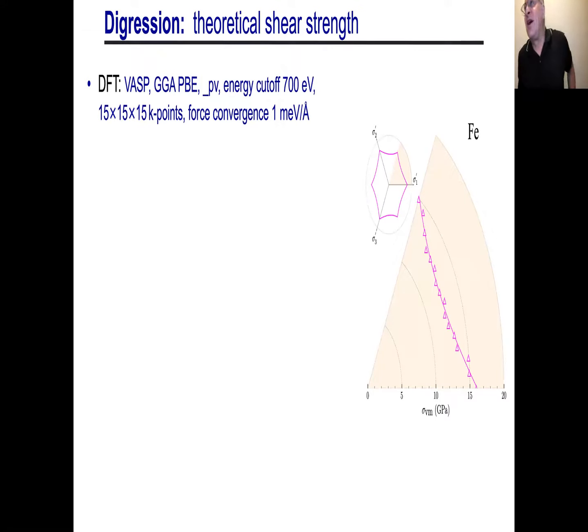Okay, I've got 2 quick digressions and then I'll get on and start showing you a lot more data. First, all the DFT calculations I show you are going to be done in VASP. It's all GGA, PBE. The energy cutoff's around 700 eV. The reason I'm telling you a little bit about the details of the DFT calculation is that for many of the things I'll show you in a minute, it's very sensitive to how well you converge the calculations, especially when I start telling you about things like theoretical strengths.